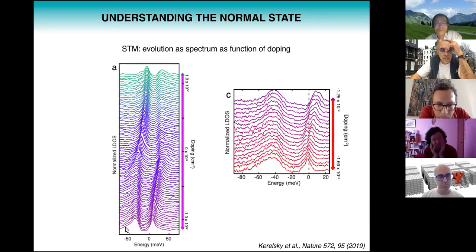But the main points are, if we look at the extrema, right? So let's look at the bottom here, and what we see is basically the Van Hove singularity close to 0, and 0 is, of course, the Fermi level, is quite sharp, while the Van Hove singularity that's further from the Fermi level is broader. And as we go to the very top, we see that it has switched, right? So here now the left Van Hove singularity is sharper, and the one on the right is a little bit broader. If we look at the dispersion of these Fermi velocities, we can also see that there is a change in their distance as a function of doping level.